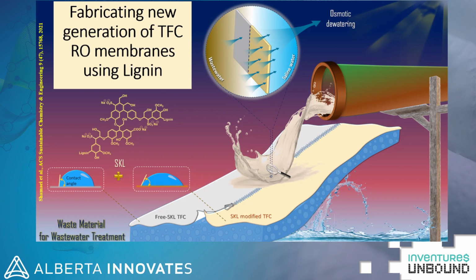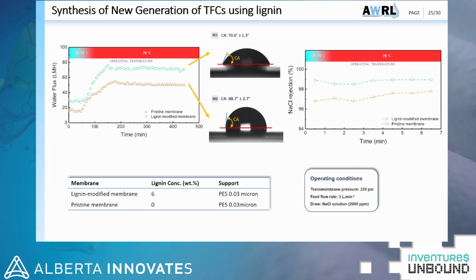We fabricated three membranes and labeled them as M1, M2, and M3, which contained 1%, 3%, and 6% of lignin, and compared their performance with the performance of the lignin-free TFC membrane, which is labeled here as M0. I just compared the results of the pristine membrane with the highest loading of lignin here. The flux results show that by adding 6% lignin, the flux increased significantly at both 25 and 75 degrees C. It can be due to the higher hydrophilicity of the lignin-modified membrane, as you can see in the contact angle results here. Interestingly, rejection also increased by adding lignin.